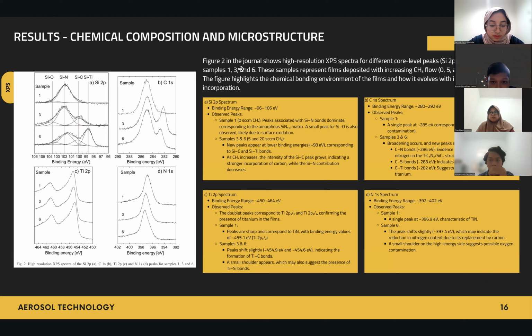So next is the chemical composition and microstructure. Here is the XPS. We can see there are a lot of peaks, four of which are Si 2p, C 1s, titanium 2p, and nitrogen 1s. The figure indicates that the peaks have different binding energy ranges. For example, for titanium 2p, we can see that mostly in samples 1, 3, and 6, the titanium is present at the same binding energy. But in the SiN, SiO, and SiTi, we can see that the presence of SiC and SiTi creates another peak, which decreases the SiN. So the SiN peak is getting lower, while the SiC and SiTi peaks are getting higher.